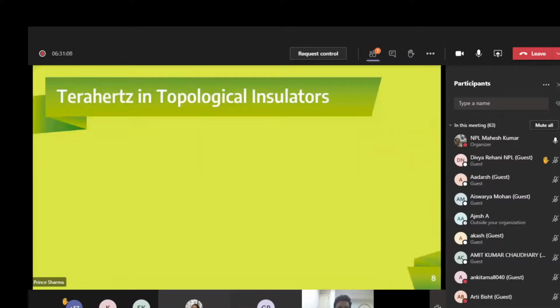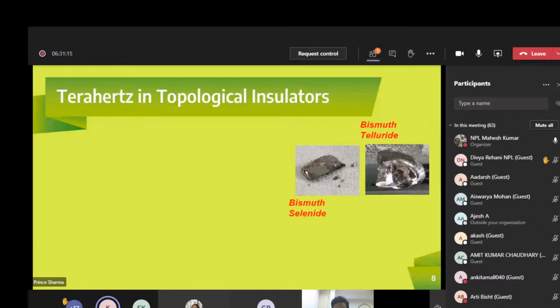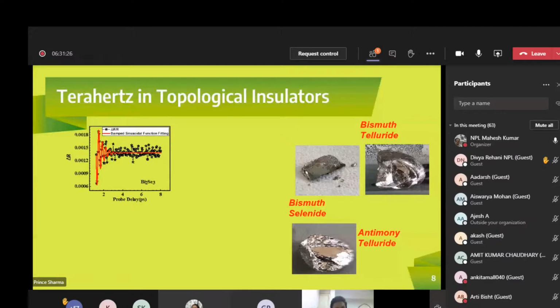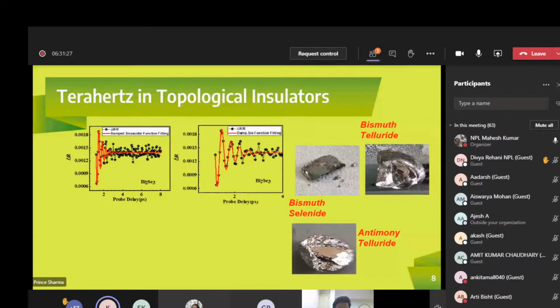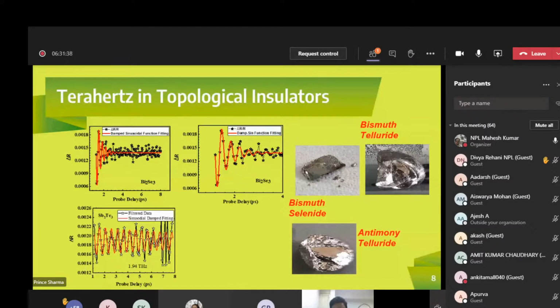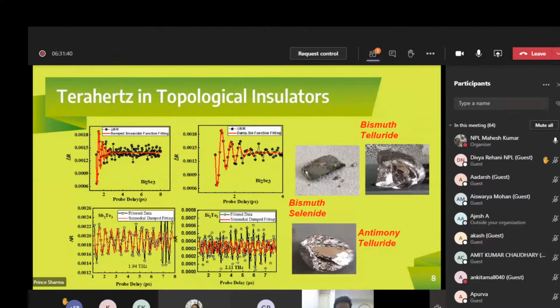In our experiment, we take 3 TIs, which are Bi2Se3, that is bismuth selenide, Bi2Te3, that is bismuth telluride, and Sb2Te3, that is antimony telluride. These are the 3 single crystals that are grown in our lab. The oscillations that are fitted in case of Bi2Se3 are shown here. These oscillations are given here, while in case of Sb2Te3 is this, and in case of Bi2Te3 is this.